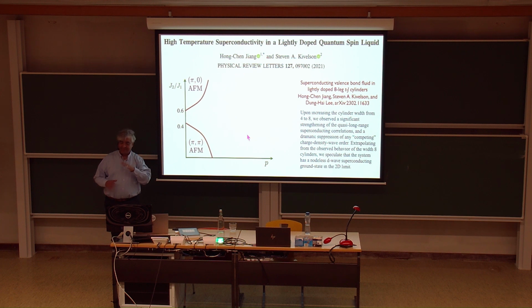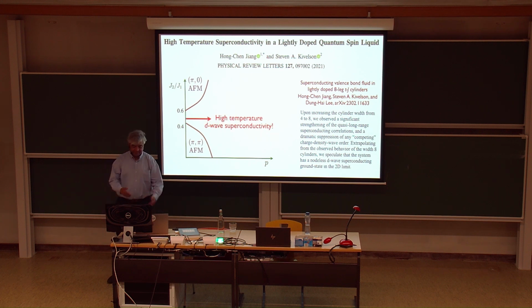Now, people have been doping antiferromagnets for decades and studying them, and in fact, it's been very hard to find robust high temperature superconductivity. It seems to compete with charge density wave order, and they're all kind of marginal. But in this case, they show numerically, in very recent work, very robust D-wave superconductivity. So this particular spin liquid, that's been my favorite spin liquid for 20 plus years, is exactly what you need to get, in fact, high temperature D-wave superconductivity. This is some numerical evidence by Kivelson and his collaborators.